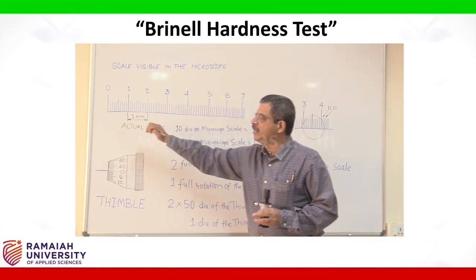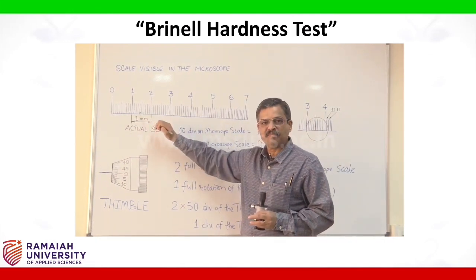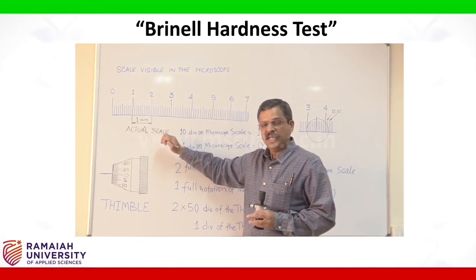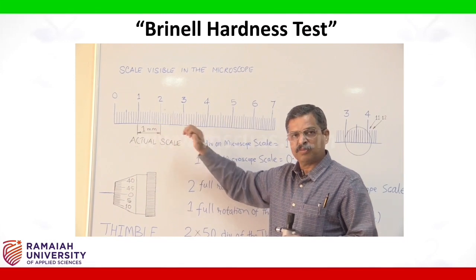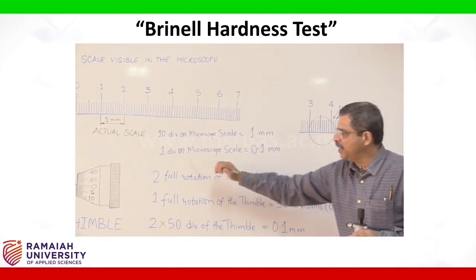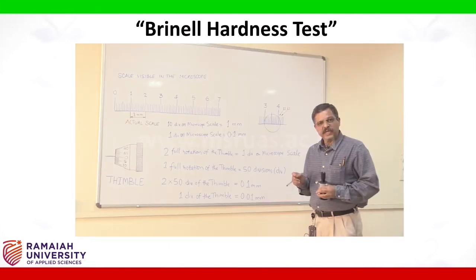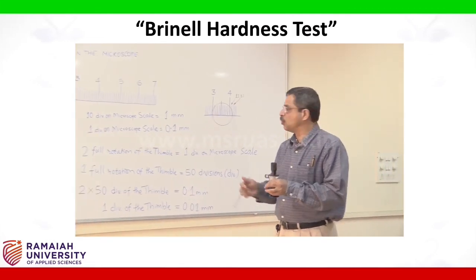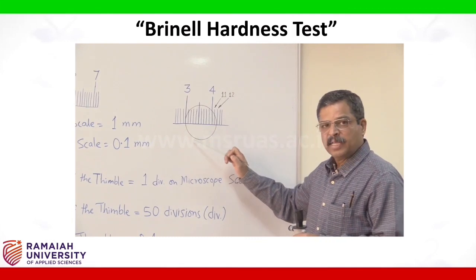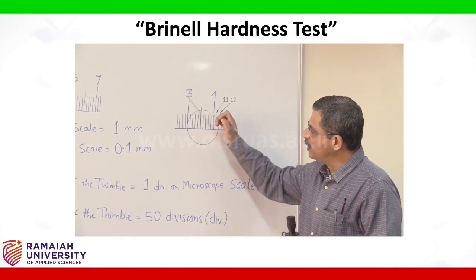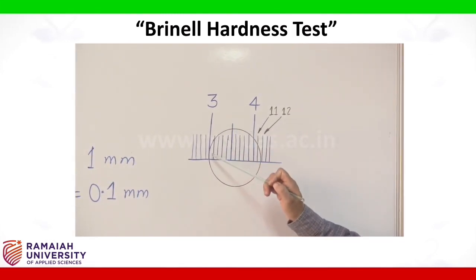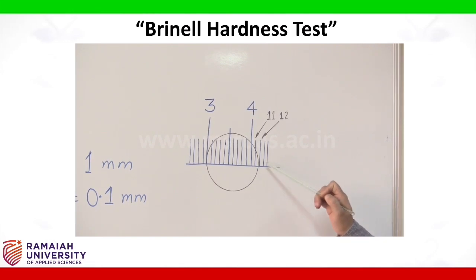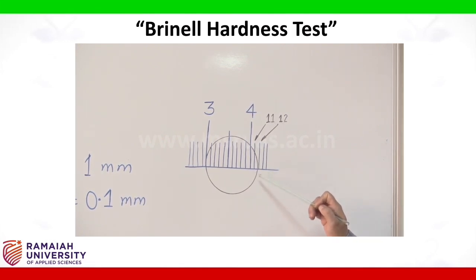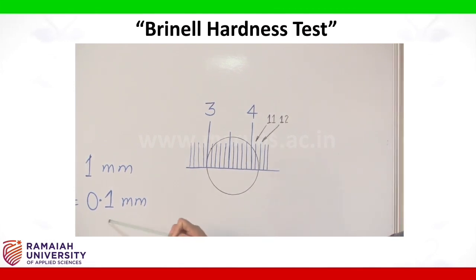The microscope scale has 7 divisions, which are further divided into 10 divisions each. 1 mm on the main scale is divided into 10 divisions on the microscope scale. Therefore, 1 division on the microscope is equal to 0.1 mm. Now, to measure the indentation, the workpiece is kept below the microscope, and one end of the indentation, indicated here in the black circle, has to coincide with one of the numbers of the microscope scale. In this case, the other end of the diameter of the indentation is between the 11th and 12th divisions of the microscope scale. Therefore, the initial reading is 11 into 0.1.